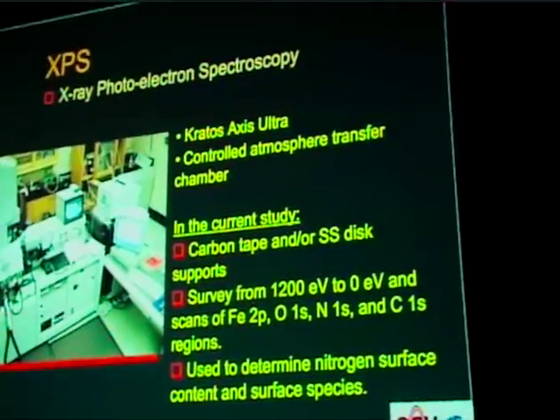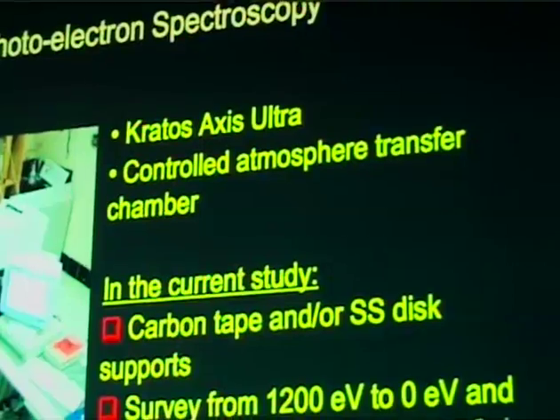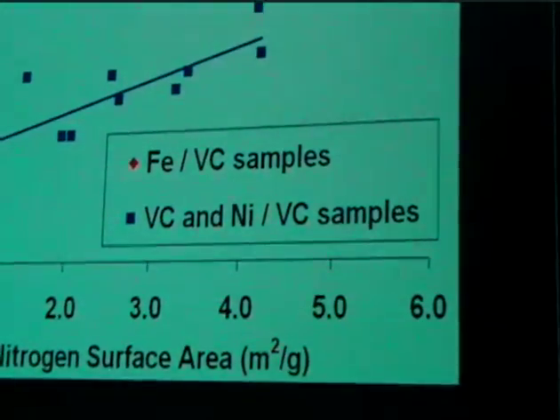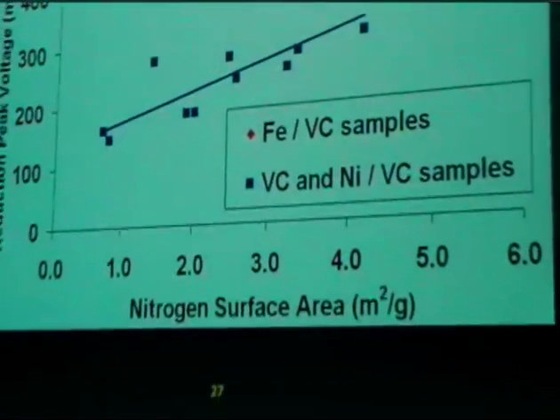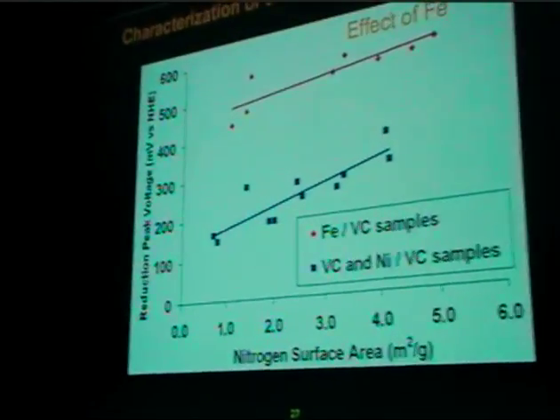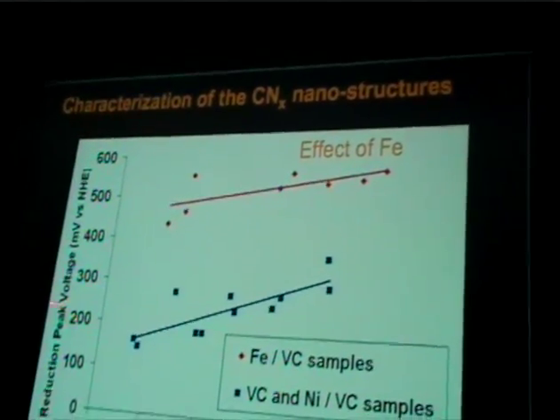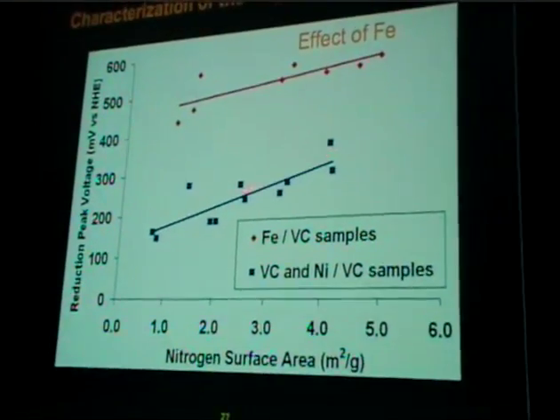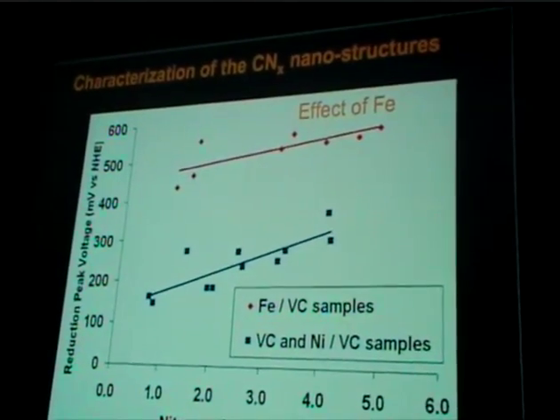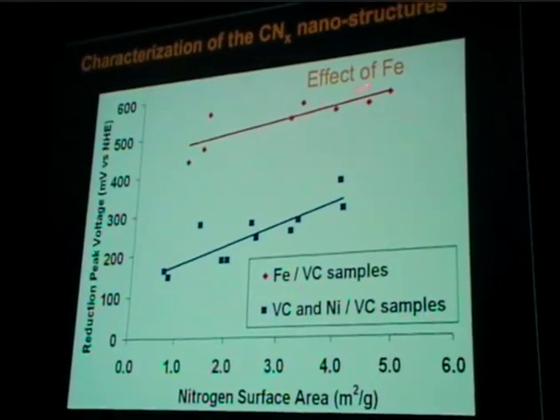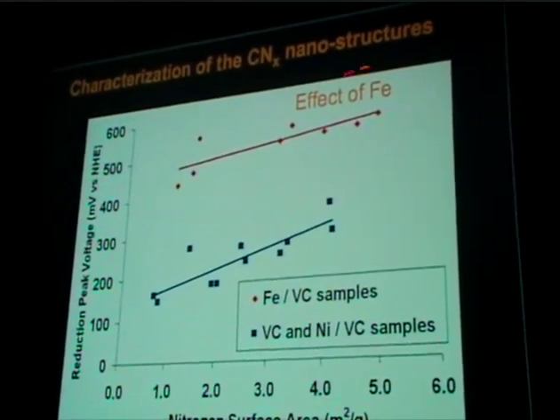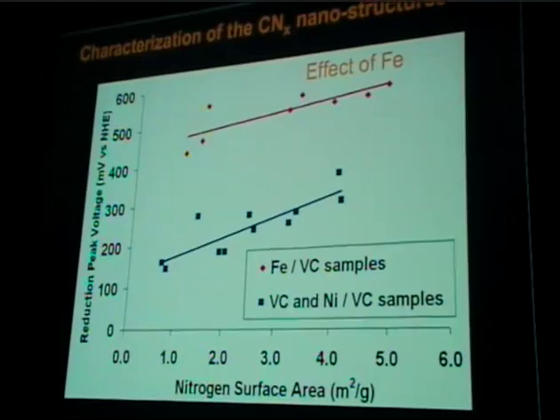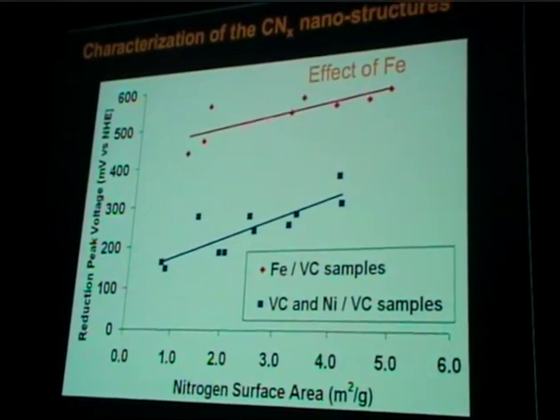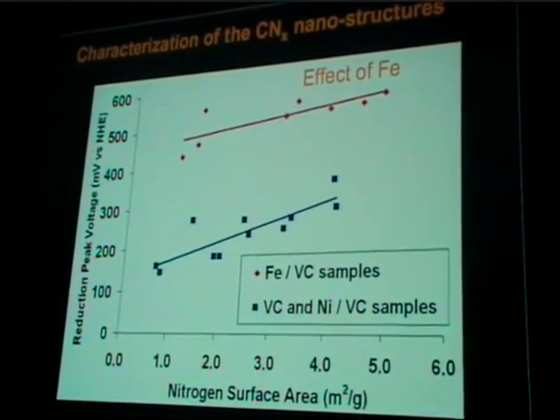What type of species do we have? We already established that we have nitrogen species. And if we look at the nitrogen content of these carbon-nitrogen nanostructures, we see that there is some correlation between the reduction peak voltage, and again, the higher this is, the more active the catalyst. So there's almost a linear correlation. However, the catalysts which are prepared over iron-containing supports have almost a step function increase in activity.